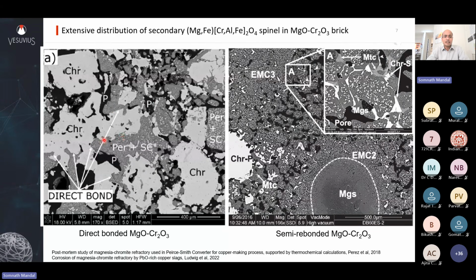What you see in here is that the chromite and magnesia that are in this, the chrome forms a complex chrome spinel, (Mg,Fe)(Cr,Al,Fe)2O4, and this chrome, the bright regions, they get inside the periclase grains at high temperature during firing, and then during cooling they precipitate out as secondary chromite. And this secondary chromite helps to bond the periclase with the chromite, the periclase with periclase, and periclase chromite with chromite.